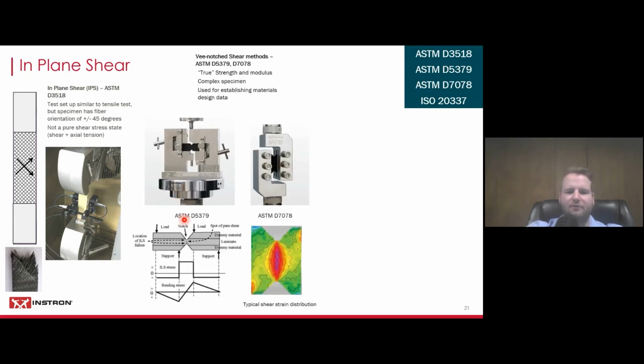For that, you need something like this, which is the V-notched shear methods, ASTM D5379 and ASTM D7078. These utilize a V-notched test specimen, so you have these V's cut into it, which is a complex specimen. This is really difficult to do. Even rectangular coupons are more challenging than with traditional materials, and now you need to make this V-notch specimen. And for the D7078, it's similar. So that can be pretty tricky. But this gives you a pure shear state in the middle of the specimen, so this is really pure shear strength. That is what you need to determine that.